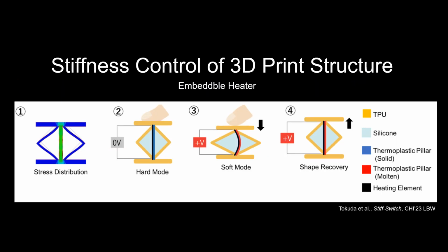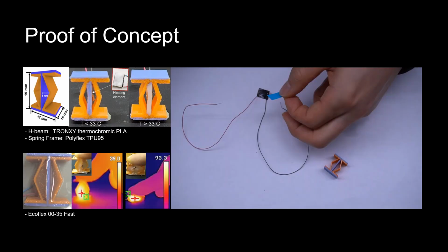We also investigated the possibility of integrating carbon nanomaterial heater in thermoplastic 3D printed structure to dynamically control stiffness. As a proof of concept, we integrated carbon nanomaterial heater in H-beam structure and control the backplane stiffness by heating the central pillar. We 3D printed H-beam with thermochromic PLA to indicate thermal state and integrated with TPU frame to add shape recovery ability. Unfortunately, heating paint was not so adhesive to the plastic and cracked as the surface was deformed.